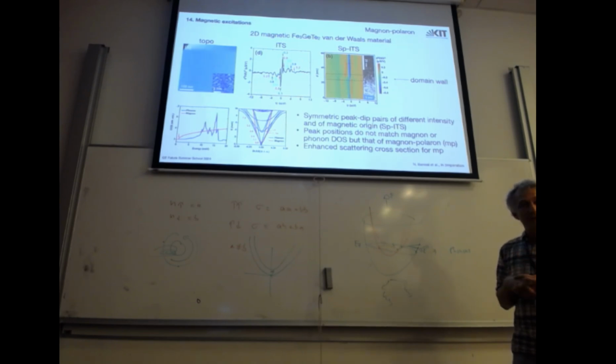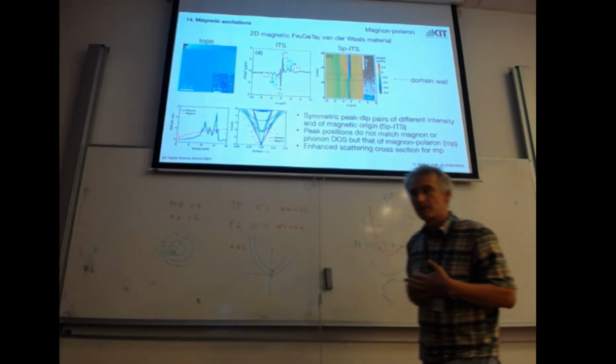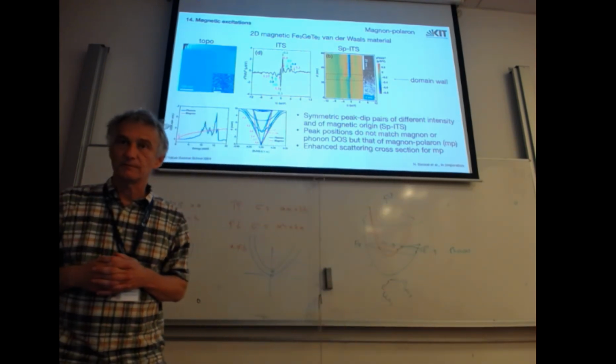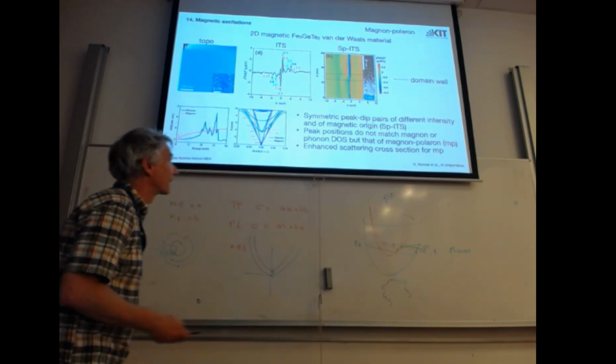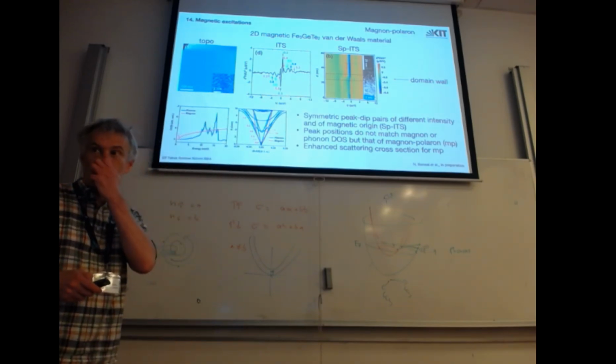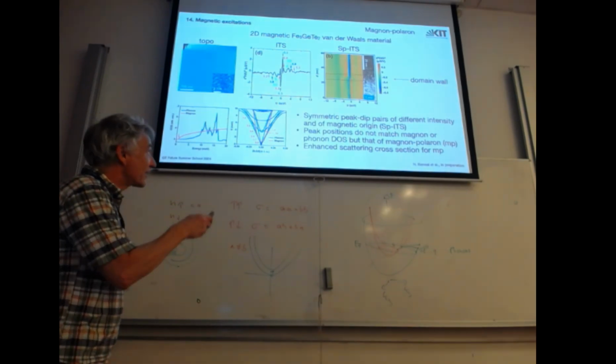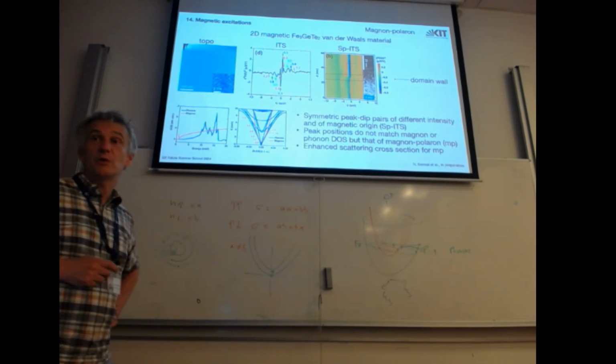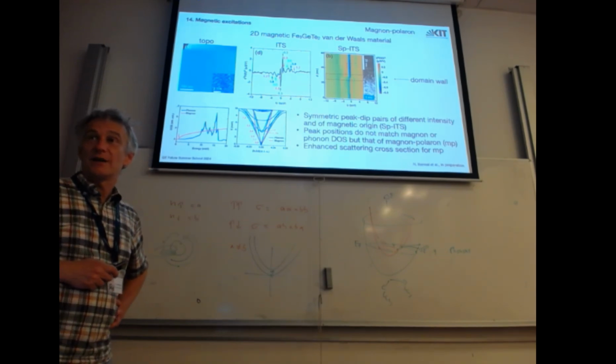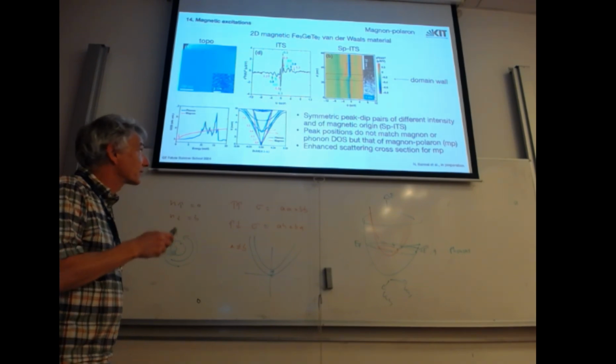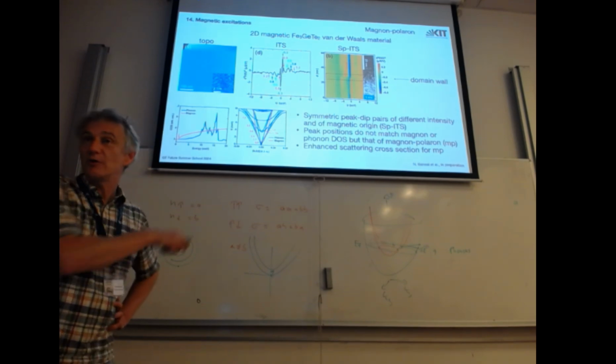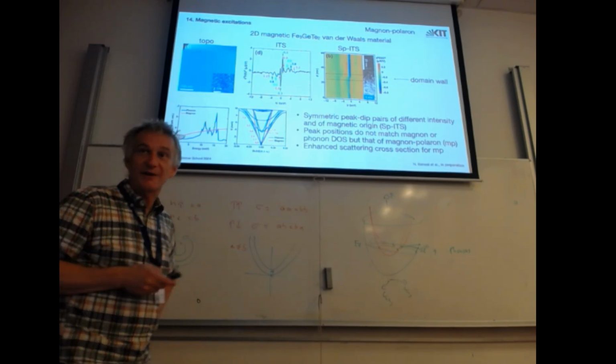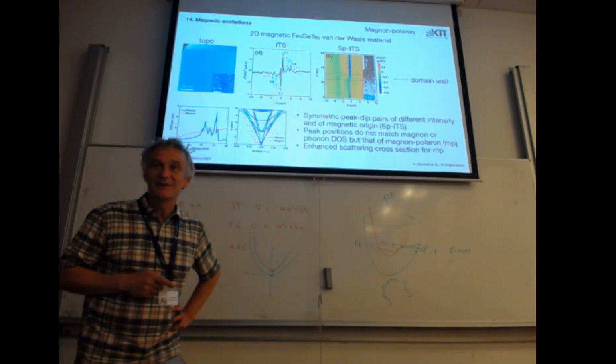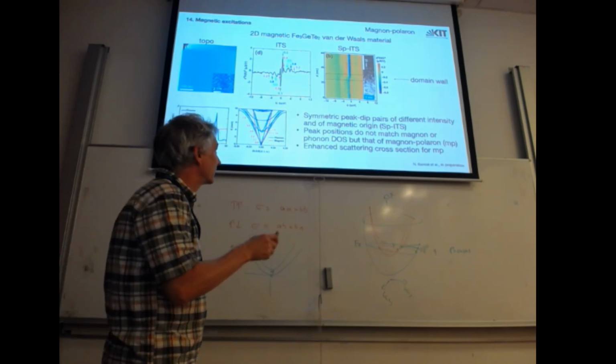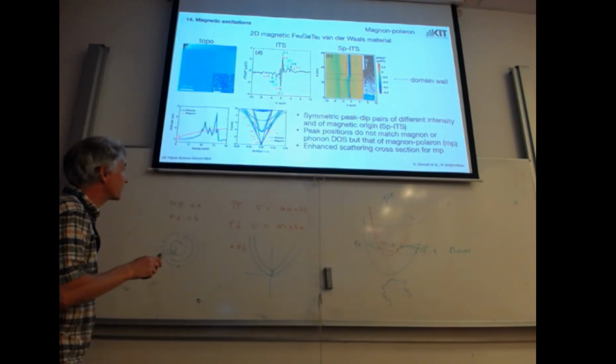They are hybridized. Yeah, but then I can ask what's the signal if I do an unpolarized experiment, right? When I just excite those phonons. Yes. And you're saying that if phonons and magnons are hybridized, I won't see any signal. So this is why we did this experiment. This follows the selection rule of magnons. Okay. And in an unpolarized tip, you don't see the magnetic domain, or you see nothing happening. You can still create magnons in your picture, first phonon and magnon, but we don't see that. So we see it only at these hybridization points.